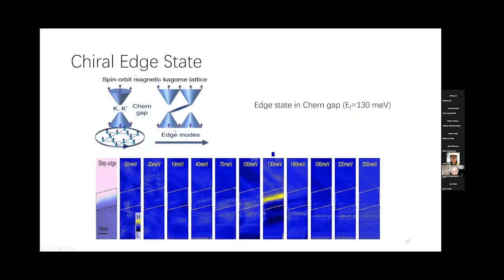After applying a bias voltage, at around 130 millielectronvolts, the Fermi energy is inside the gap. So they also detected a chiral edge state in the STM spectra. So this is consistent with the theoretical prediction.